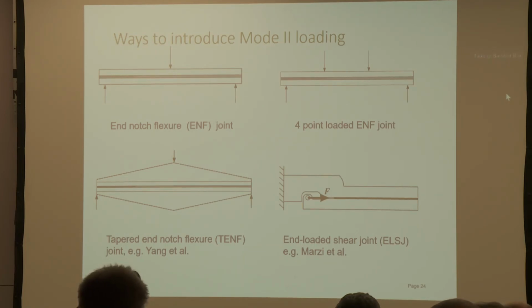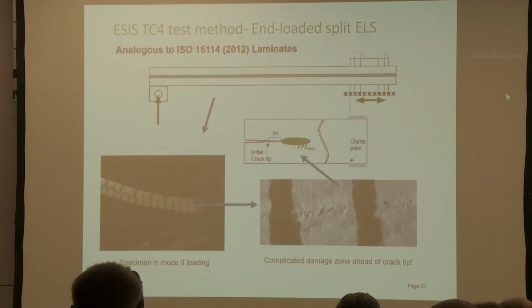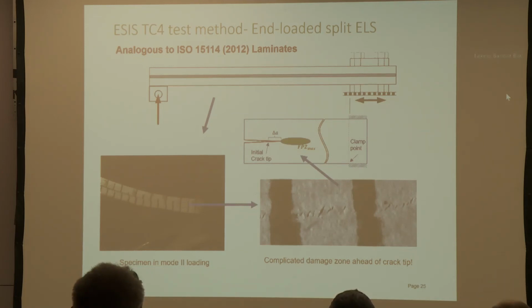Different workers have used different ways of doing this, and at Imperial and in the ESIS TC4 committee, we've used the end-loaded split. This is a specimen which is clamped as a cantilever, and the clamp is based upon a linear bearing trolley, and then the specimen is bent, and that introduces a state of pure shear at the crack tip. And of course, what then happens? Well, as you deflect the beam, you impose the shear stresses at the crack tip. And if the adhesive is a highly toughened adhesive, as are many of the adhesives that are of interest, then an extensive fracture process zone develops. And this can be really quite extensive in Mode 2.